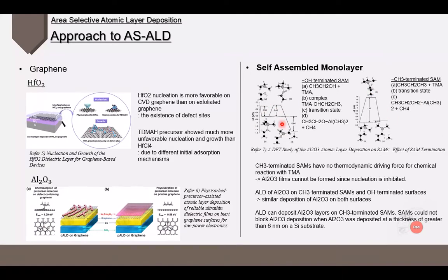However, the method also has limits. SAM treatment cannot prevent deposition permanently. As the ALD process proceeds, SAM chains are getting damaged. If oxidant functionalizes the methyl group to hydroxyl group, the deposition reaction can be conducted. It starts the deposition on damaged SAM chains as nucleation sites.